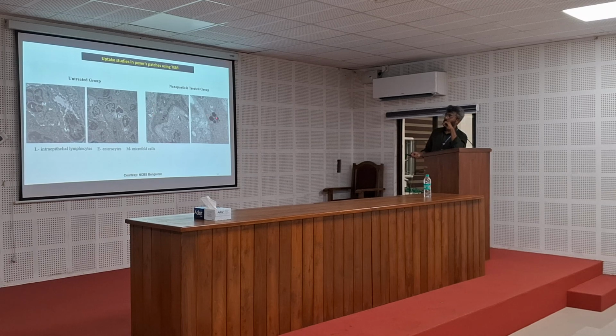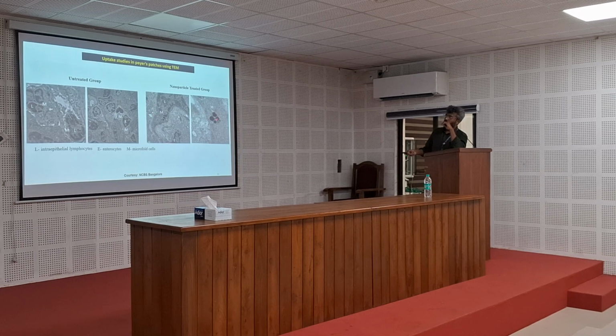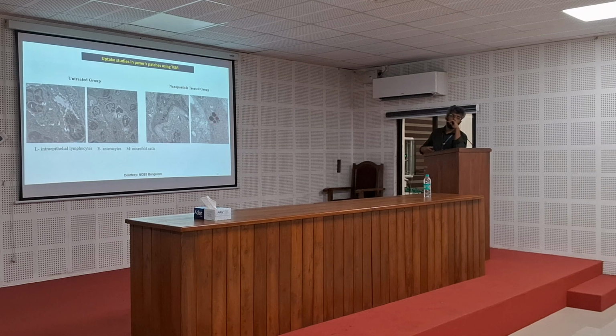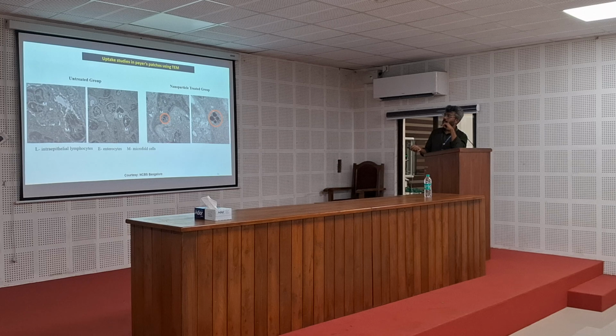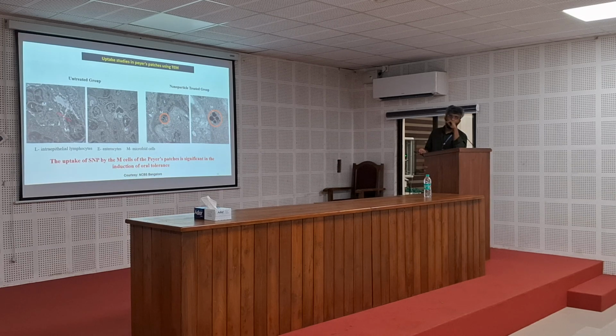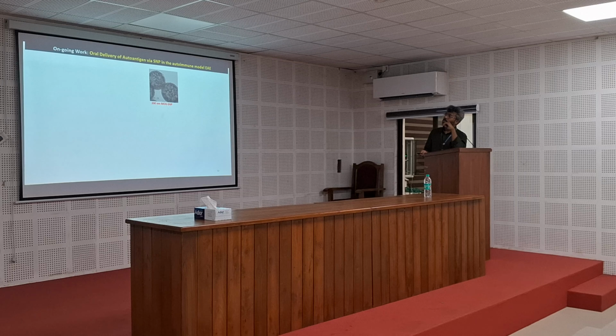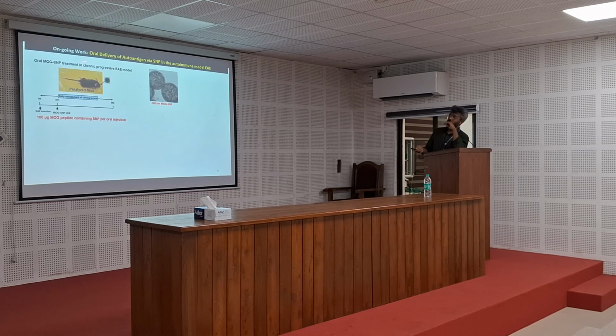So this is an untreated group and this is a treated group. We were able to see that our particles are accumulating in the Peyer's patch, which is very important for inducing oral tolerance. So that is the image of that. This uptake by Peyer's patch is very significant in the induction of tolerance. Once we saw that it is accumulated in the Peyer's patch, we gave the treatment, this time through the oral route. Earlier it was the IV route.